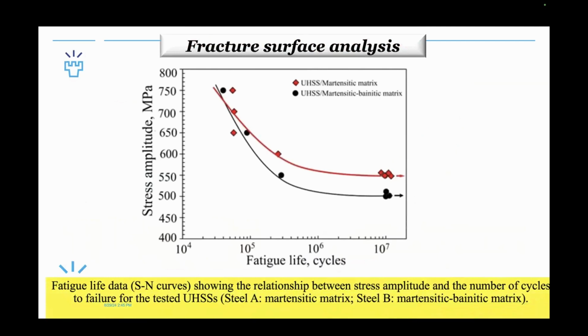Now we come to the fatigue S-N curve. We found, of course, that this is the martensite steel A. You can see the fatigue limit is higher than for steel B, martensite-bainite. This is the fatigue limit here: 550 megapascal, and this one 500 megapascal.